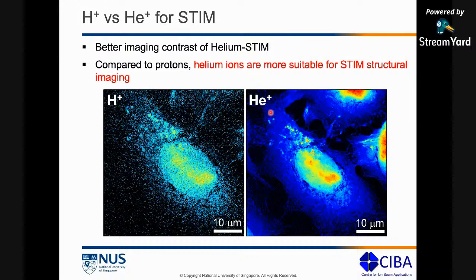But helium being heavier, if we are doing helium STIM, we need to be careful as to how thick a sample we are putting in. If the sample is fairly thick, you're not going to get any transmission of helium through your sample because it's quite heavy. It's going to get stuck in the sample itself, and then you won't have any imaging at all. Whereas protons being lighter, they have a much better depth into your sample, and we have the flexibility to use slightly thicker samples as well. So if you're willing to lose out on the imaging contrast to a certain extent, we are better off using protons, because for certain sample thickness ranges, we will definitely have a transmitted signal coming out. There are pros and cons to both, and most of the time we use protons for STIM imaging.